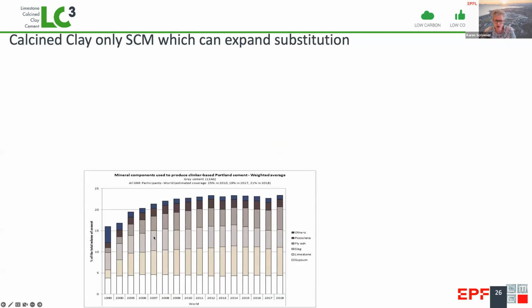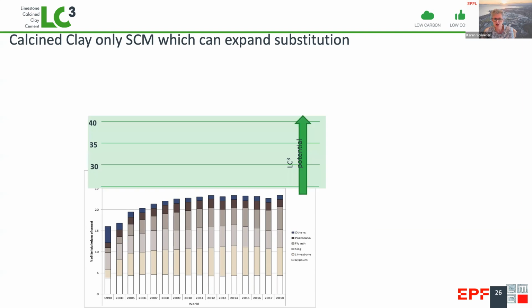Well, this graph here shows the average levels of substitution worldwide from the GCCA figures. And you can see this has stagnated at only around 20% for the past decade or so, due to the lack of availability of slag and fly ash. But if we remove that limitation, we can go to a clinker substitution level of at least 40%. And on a time scale of 2050, we could probably go higher than this.